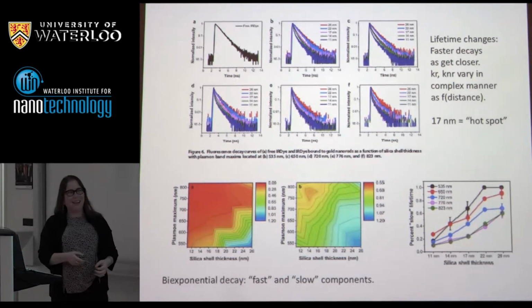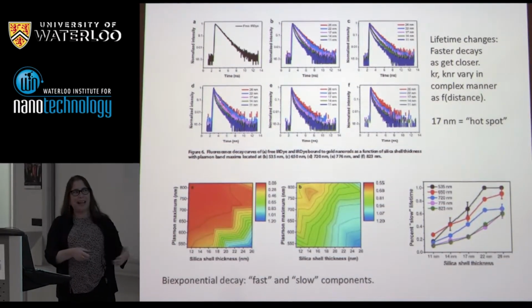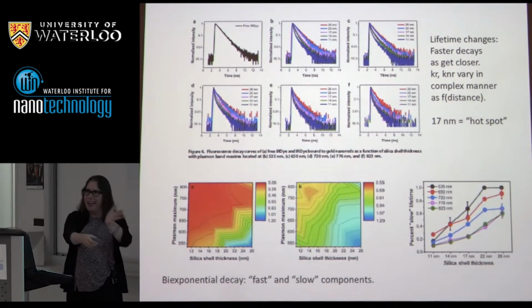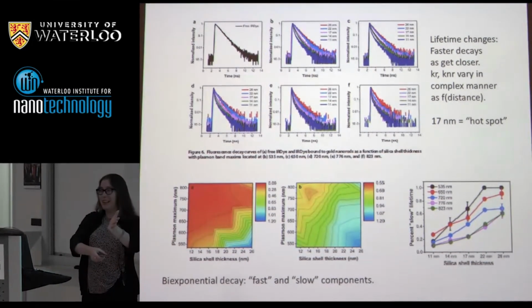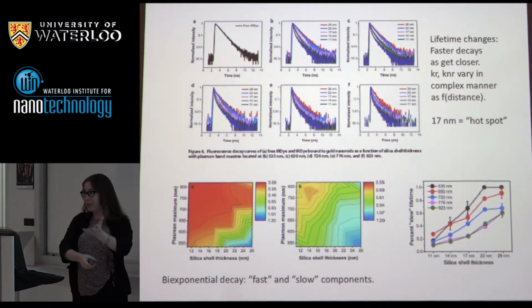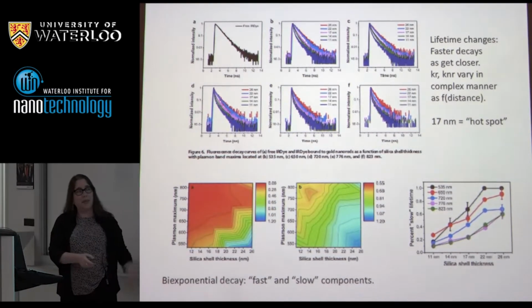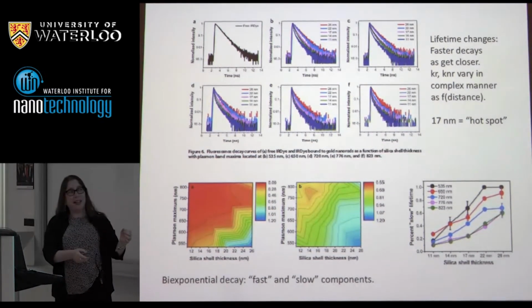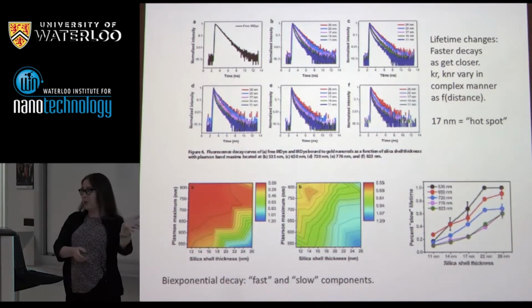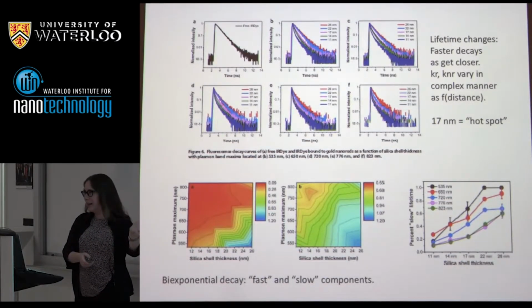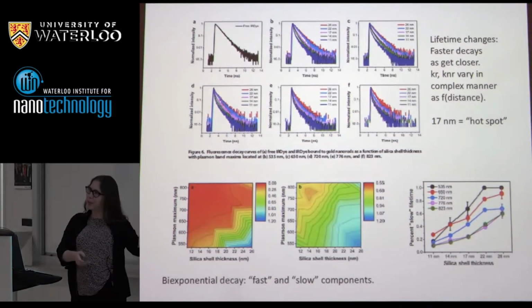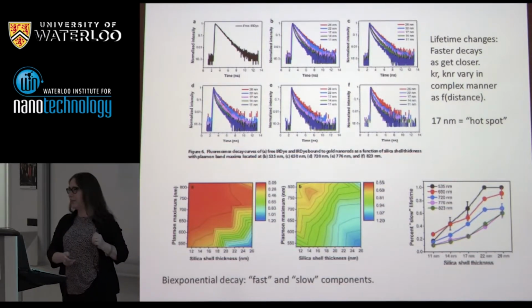So what they found in their paper, they had these beautiful maps of kr and knr varying as a function of distance. So it's really a complicated system in the end, much more than I thought. But what do they conclude? Generally, 15 nanometers out is what they calculate is where you want to be if all you care about is getting more light out of your fluorophore. We find 17 experimentally, so we declare victory. Okay.